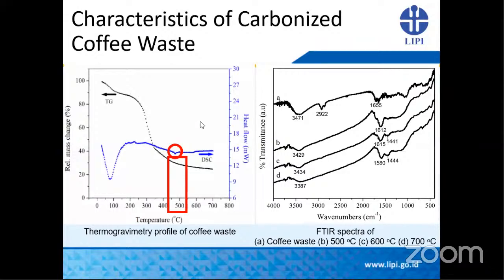So this is the characteristic of the carbonized coffee waste. At first, we try to examine the thermogravimetry profile of the coffee waste. In here, we can see for the treatment below 500 degrees C, there is still some small peak here. So we can know in here below 500 degrees C, there is still some functional group in the sample. So we cannot use the temperature below 500 degrees C because some of the remaining volatile will remain in the sample. So we have to carbonize the sample above 500 degrees C.